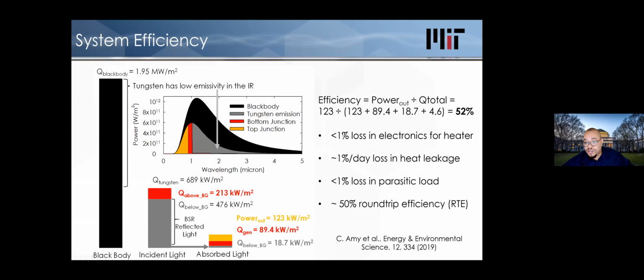We're also expecting to lose less than 1% or so in the electronics for the heater. So you got to put in a lot of current to drive that heater. We're also expecting to lose roughly 1% or so per day in heat leakage. There's also on the order of 1% or less parasitic power consumption, pumping the coolant around and keeping the cells clean. And so we expect in the end, we're going to end up with about a 50% overall round trip efficiency after you account for all these penalties. So our 50% is what we think is a real 50% for round trip.